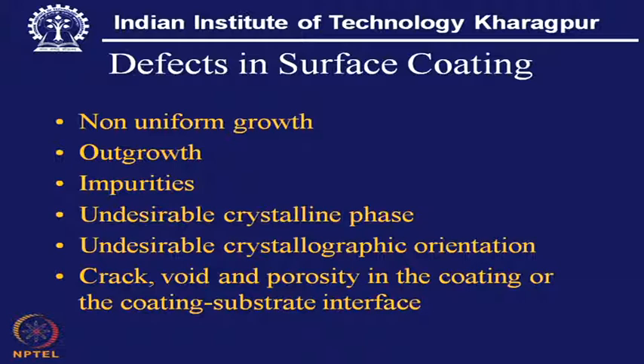We have also what we call outgrowth in certain places, and that looks like a mountain in those areas, very easily identified. Unfortunately, because of some reason, whether it is in the gas phase or say the metal donor or the contamination comes from the reactor itself, it is an unfortunate eventuality and some impurities got into this coating.